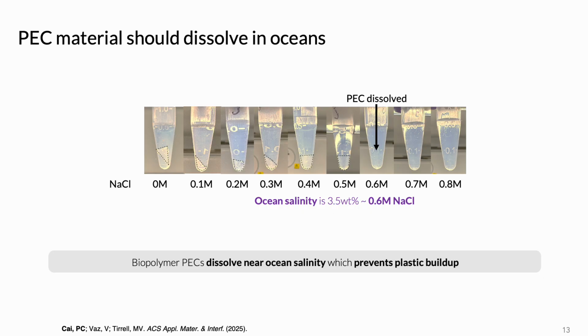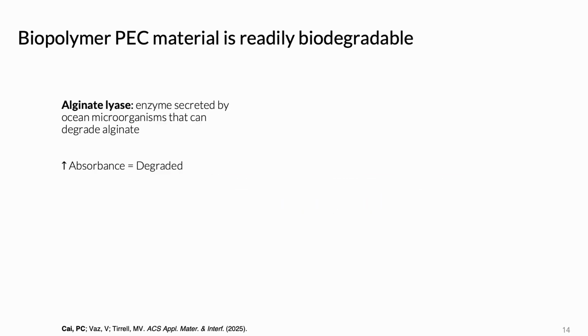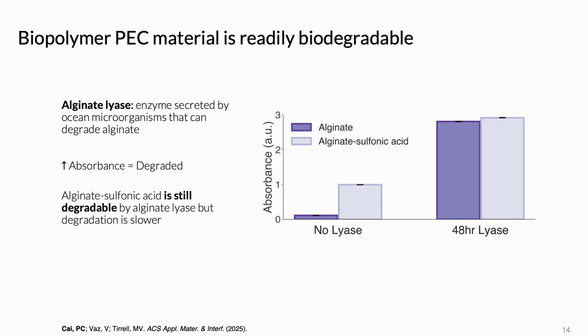And since the basis of these materials are polymers derived from ocean organisms like seaweed and crustaceans, it's likely that the ocean microorganisms have the capabilities to break down the dissolved biopolymers. To verify this, I measured the degradation of the alginate component of the biopolymer PEC material by an enzyme called alginate lyase, which can be found in ocean organisms. The test measures absorbance over time, with greater absorbance indicating a greater degree of degradation. After 48 hours of incubation with the enzyme, the modified alginate was degraded just as much as the unmodified natural alginate.